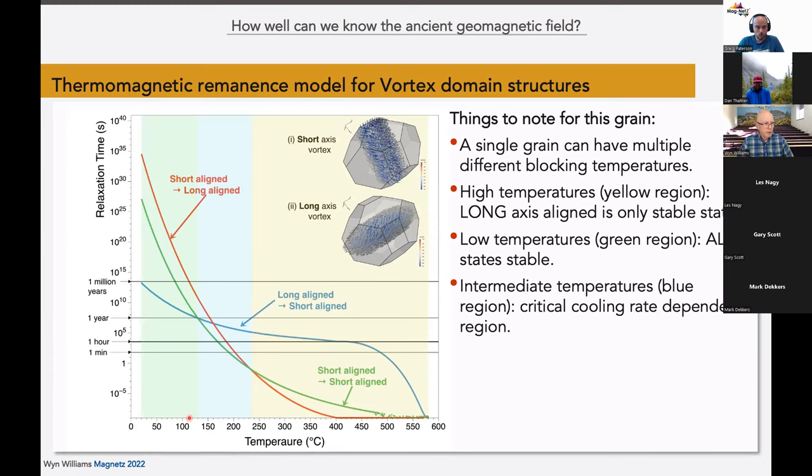So we speculate here, and what I'm going to use in our model is that such grains might have a more complex thermomagnetic response, and we're going to use an example of such a grain to see what that might mean in terms of a PSD TRM model, kind of a worst-case scenario, if you like. So this is the grain that we're going to concentrate on for the rest of this talk. It's a 100 nanometer cube octahedral grain, 30% elongated along the 1-0-0 direction, and it has several blocking temperatures, but the major blocking temperature is about 200 degrees centigrade or so. So it can nucleate a stable vortex domain structure along the 1-0-0 or minus 1-0-0 direction. That's along the long axis of the grain, and there are four other stable vortex states along the short axis.